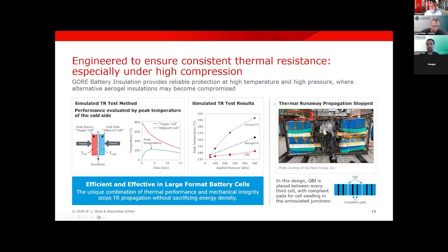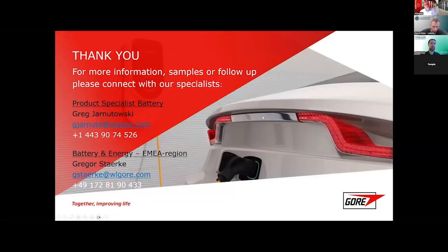And as last point, this is a picture of one of our partners that did a test. So they initiated thermal propagation at the middle cell. And in this design, the GBI is placed between every third cell with compliant pads for cell swelling in this case, and in the insulated junctions. So what you could see here, although the thermal propagation was initiated, this material stopped the thermal propagation at this point. So this was more or less everything in a nutshell.